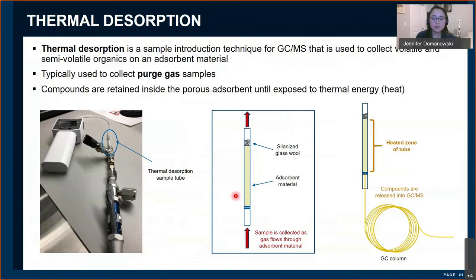So the way this works is we have our sample tube. So this is a typical sample tube that would be used for this. And it's filled with an absorbent material, which is a porous polymer resin. So we'll flow the gas through the tube. And as the gas flows through, any volatiles or semi-volatile organics will be collected and trapped in those pores. And then it'll stay there until it's exposed to some type of heat. So what we do is once we collect our sample, we take this tube and put it in our GCMS instrument. We'll reheat it up. And as the sample heats up, it will release everything that it's trapped into the GC column, where it will separate out, as I described earlier.